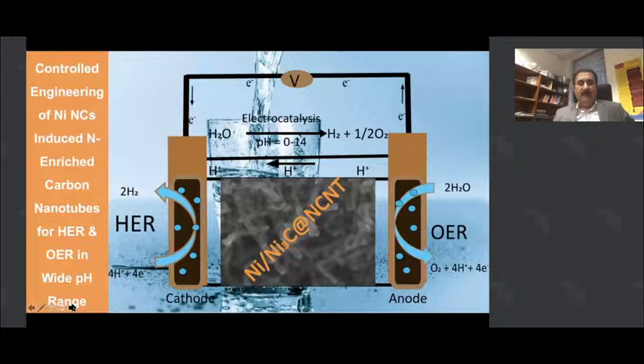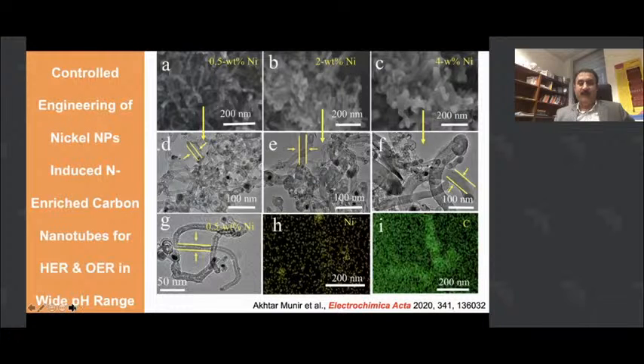In another case, we used these nickel nanoclusters and nanoparticles as catalysts to grow nitrogen-enriched carbon nanotubes. Depending on the size of these nickel nanoclusters or nanoparticles, we were able to control the thickness and diameter of these nitrogen-enriched carbon nanotubes as well.